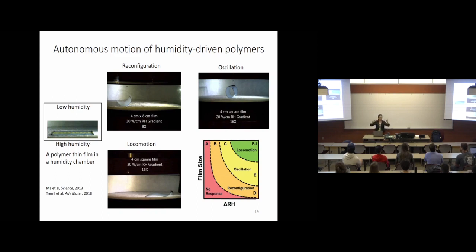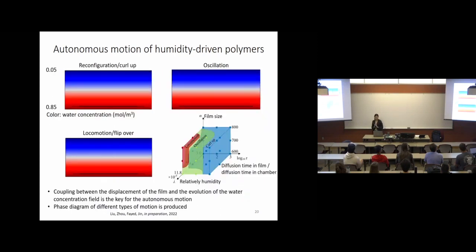If you have a thin film, the humidity difference between the top and bottom is very, very small. So what is causing the bending? And moreover, this crazy motion. I didn't understand what's going on until we analyzed this carefully. We realized the key thing is that the film is deforming, so it moves to different locations. On the other hand, although the water can diffuse through the film, it's very slow. Therefore, essentially, it's an impermeable film in the short term. Therefore, the film itself is changing the humidity distribution as well.